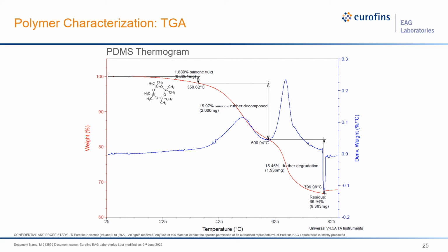So what other techniques can we use to characterize this material? Next, we analyzed it using thermogravimetric analysis, or TGA. This technique involves heating a small amount of the sample, usually just a couple milligrams, under a nitrogen atmosphere from ambient conditions up to 800 degrees C, or about 1500 degrees Fahrenheit. As the sample heats up under nitrogen, small volatile components can evaporate or volatilize, and this is observed as a mass loss. As you reach higher temperatures, you can start to degrade and decompose the polymer, and again, you can observe this as a mass loss event.